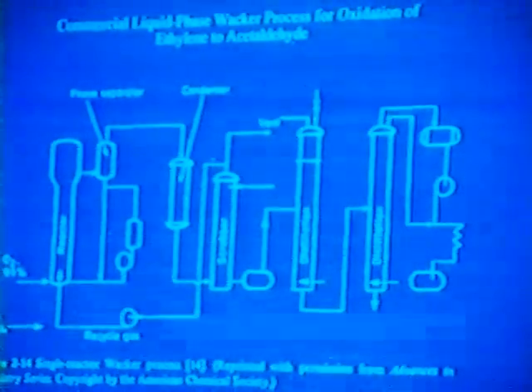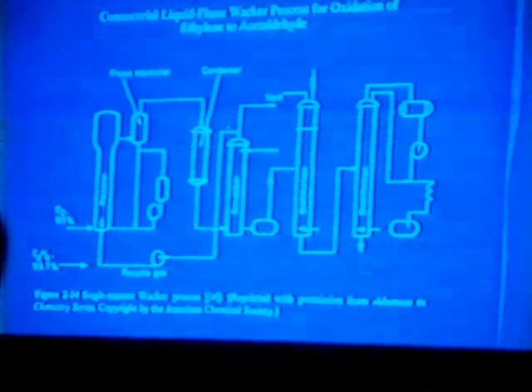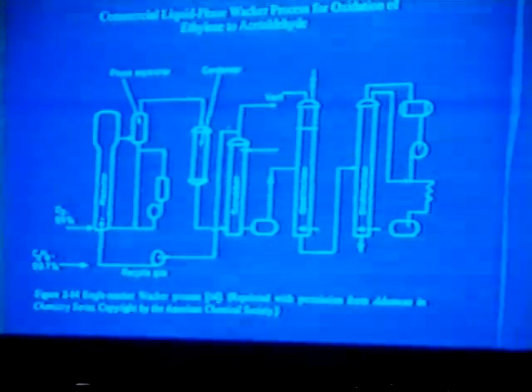Having established the overall design factors for a supported molten salt catalyst, we looked for an example with potential applications. We picked the Wacker process for the production of acetaldehyde from ethylene oxidation. In this process, a cuprous chloride–palladium chloride catalyst solution is contained in a reactor, and reactants ethylene and oxygen are bubbled through it. The product acetaldehyde is formed, and the liquid catalyst solution must then be separated in distillation columns and recycled back. Our objective was to develop a catalyst that would eliminate those distillation columns, eliminate the severe corrosion problems in the process, and increase the effectiveness of catalyst utilization.